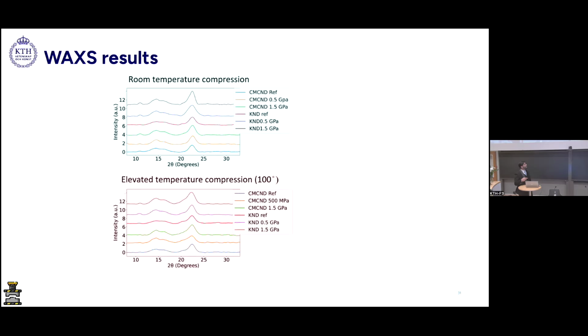But in the carboxymethylated pulp, the system was a little bit messy, which we wanted to explore further in a computational manner. The reason behind this could be that you have inaccessible water, slightly accessible water, and free water in the system. When you compress this system, except for the very inaccessible water, most of the water is squeezed out, and you have a fibril bundle, which is a compact structure. That fibril to fibril interaction and the signals produced due to the interfaces contribute towards the higher crystallinity of the sample.